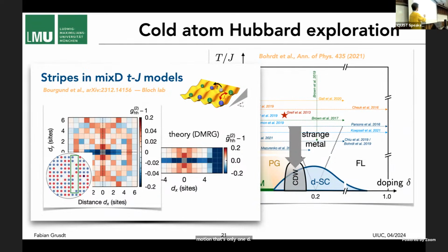This is a G2 plot, a correlation of holes. You can see if there's a hole in the middle, there's this reddish signal going up. That means it's quite likely to have more holes joining along this direction. It's blue in this direction, which means holes in the same chain would repel each other. This is a snapshot, and there's a stripe-like structure of holes forming. If you look a little bit at this signal, there's another red spot over here. That may actually be a sign of charge density wave patterns forming: there's a hole here, and then at a certain distance, another stripe of holes forms. At this point, though, the temperatures are too high for us to conclusively say that they fully see these patterns. But these correlations are statistically significant, so we do know that the holes tend to bunch along these vertical lines.